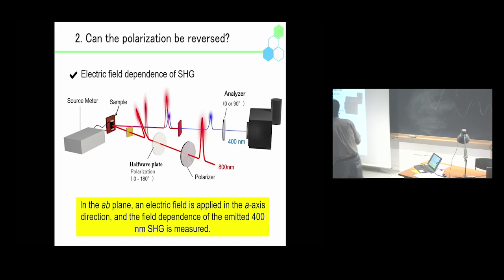So here is the experiment setup. You can see the sample, the crystal, here. We fabricated some electrodes with silver paste, and we apply the electric field with this source meter. While applying the electric field, we irradiate the crystal with an 800 nanometer pulse. After that, we detected the generated 400 nanometer SHG pulse using the appropriate filter, monochromator, and photomultiplier.